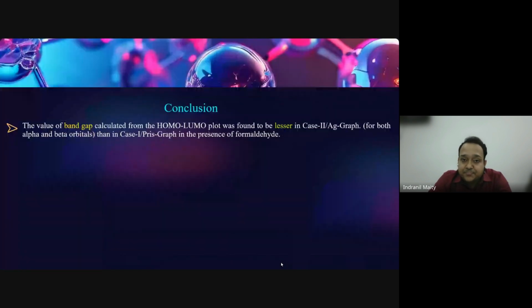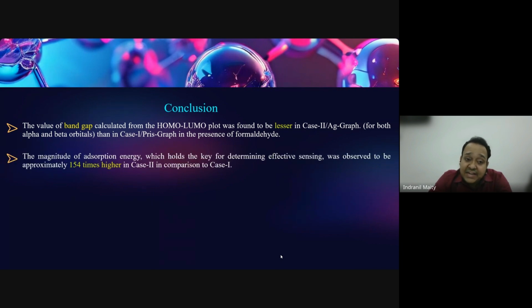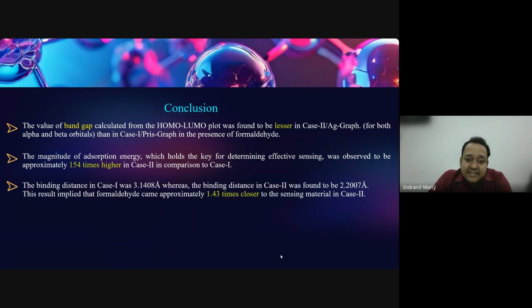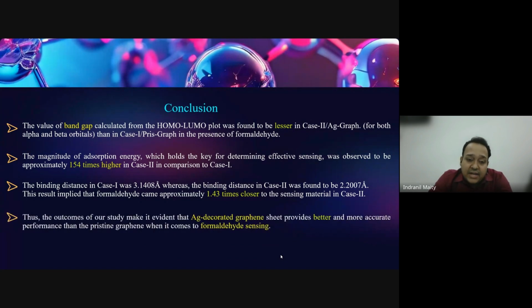So in conclusion, the band gap in the HOMO-LUMO plot was found to be smaller in case 2, that is silver doped graphene, compared to case 1. And the magnitude of adsorption is significantly improved in case 2, by 154 times. And the binding distance, as I already mentioned, is reduced from 3.14 to 2.2, so a 1.43 times reduction. Finally, we can conclude that if the material is doped with a foreign atom or silver nanoparticles, the silver decorated graphene will be an effective sensing material for the detection of formaldehyde, and it can be useful for gas sensing or vapor sensing applications.